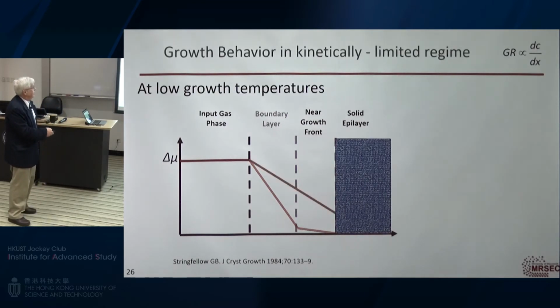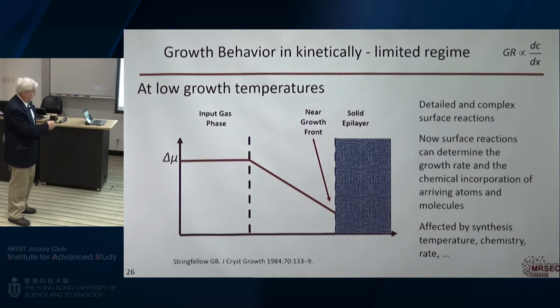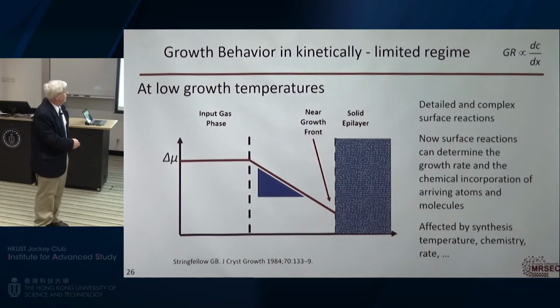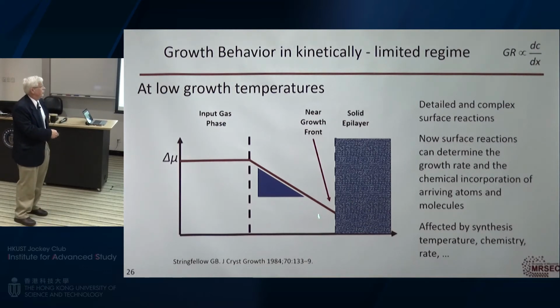I can actually go to much lower temperatures, and now the incorporation of atoms actually takes much, much longer than the transport time of a new atom to the surface. And now the growth is going to be determined by these chemical and surface reactions. And I can manipulate those in ways that are advantageous.